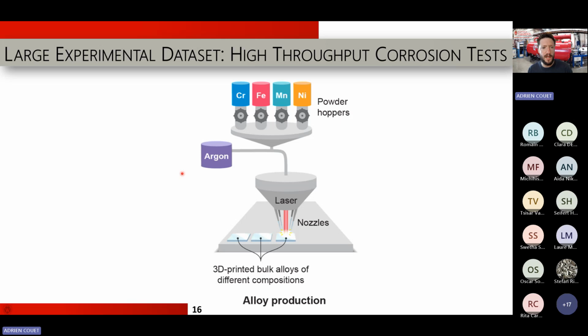So we are producing alloy using additive manufacturing because it's a very fast approach to produce metal parts of relatively well-controlled composition, relative to arc melting, which can be relatively fast, but it's very labor intensive and also not as fast, of course, as additive manufacturing. So here is how we process. We have chromium, iron, manganese, nickel. Those are powder hoppers of single elements. We are, of course, looking at other powders, refractories, and so on more lately, but this is more of a case study to look at stainless steel-like elements, those 3D transition metals.